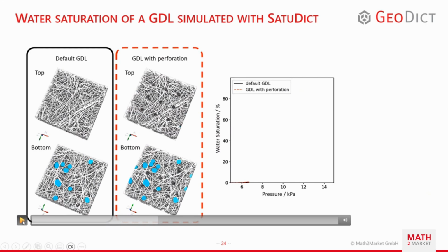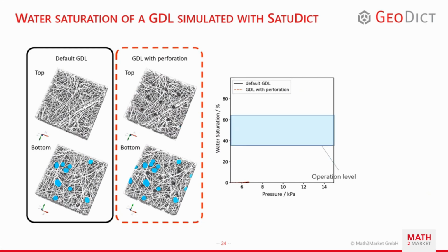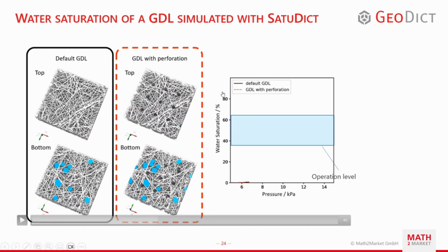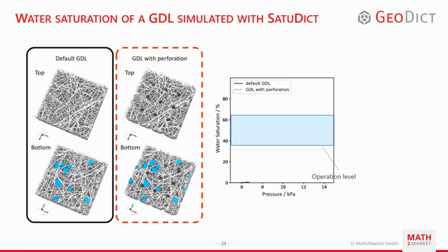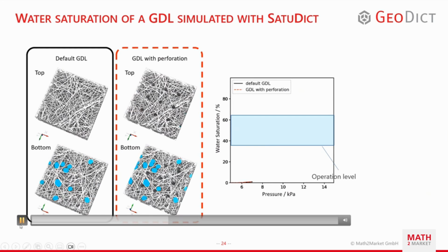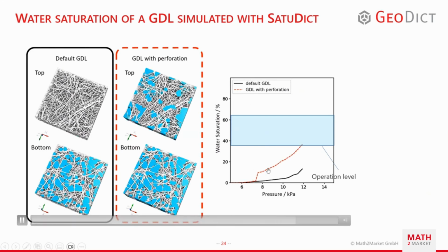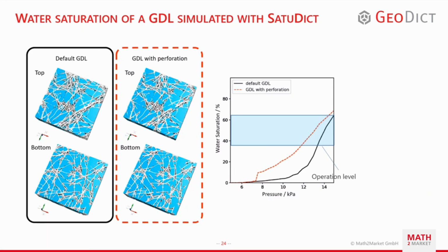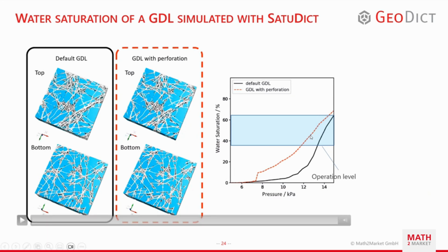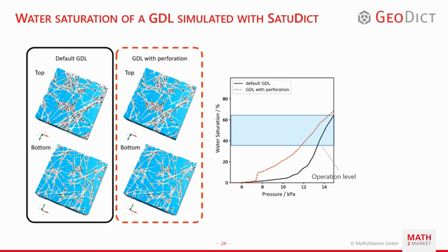If we look at the graph here, on the y-axis we have the saturation with water in percent of the two GDLs. And on the x-axis, we have the pressure that is needed to get the gas through the structure. And if I let the video run, we can see that for the perforated GDL in red dashed here, we get a different graph than for the default GDL. In the typical operation level, we see that we need less pressure for the gas to go through at the same saturation level than for the non-perforated GDL.